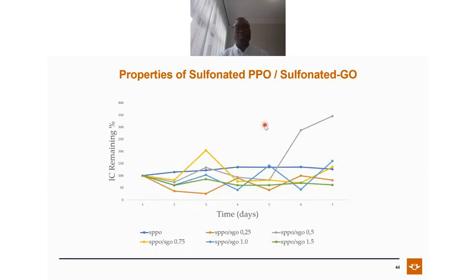We also looked at the properties of this material in terms of degradation. Something interesting also happened, which we're still looking at. This material degradation was done over 7 days. We also want to do it over 1 month, 2 months, and 3 months to see how they work. But what we found out is that if you normalize all of this, there's no degradation happening. Instead, it's telling us that there's enough water uptake, which means there's a high solvation process, which means there's a high amount of uptake of the OH. That's why you see it's increasing. So instead of the ion conductivity decreasing, it actually increased because the membrane is able to accommodate enough water and actually increase the ion conductivity. Then the OH assumes ion conductivity. We are able to say this if we leave the material in an OH solution for a longer period of time, the OH actually does not degrade the membrane, it actually accepts it and leaves it in the system.